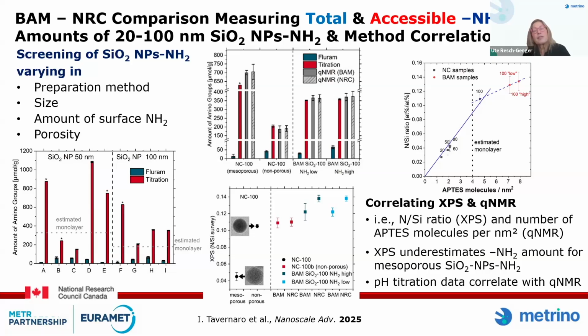And one of the reasons why I show you this is when you look now into the particles, we had mesoporous and non-porous particles. For the non-porous particles, we had a relatively good correlation between XPS and qNMR. But for the mesoporous particles, well, it didn't work out. The reason for this is also quite natural. For NMR, you dissolve the particles. Well, you grab every functional group which is there. Protons are small enough to penetrate the pores. The dyes, maybe one dye has a chance, but that's it.